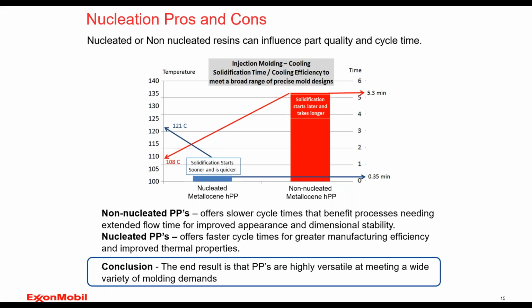But pros and cons is the key thing here, in that not always does a nucleated resin help your injection molded application. If the flow properties are such that areas of a part will cease to flow, meaning they've reached the end of their flow destination, and other areas within the cavity are still flowing, that's going to be offset cooling. Once a resin ceases to flow, it has nothing else to do but cool and solidify. When that occurs, it can lead to that warpage and dimensional delta that I talked about, and that could be detrimental to the actual application in terms of warpage. So there's benefits to having a non-nucleated grade. That basically means you're going to get a wider processing window at the expense of maybe efficiency and cycle time.